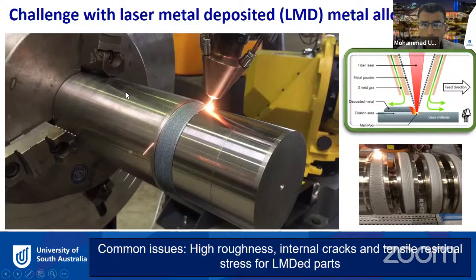And we have also recently applied a similar technique, the ball burnishing technique, onto laser metal deposited alloys. For example, this is one of the laser cladded processes. So generally, we can deposit the coating onto the metal components to repair them. However, the problem with laser metal deposited alloys is that the surface is very, very rough. This is one of the components after the laser cladding. And there might also be other inherent properties like porosity and cracks.